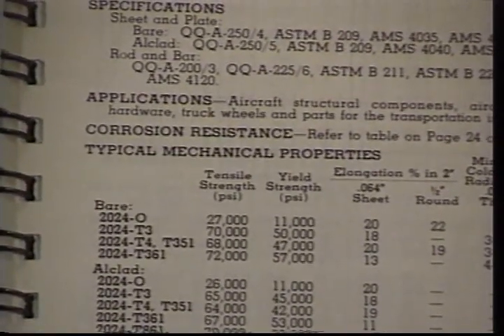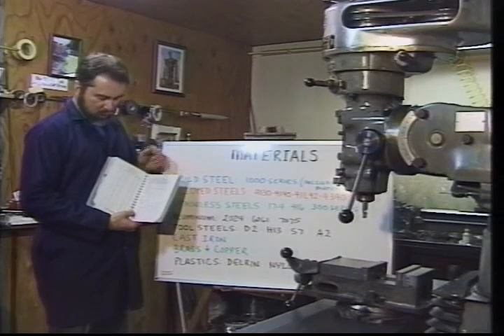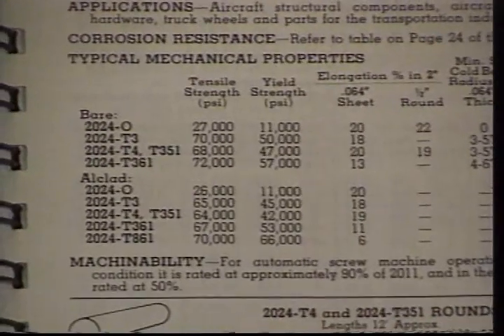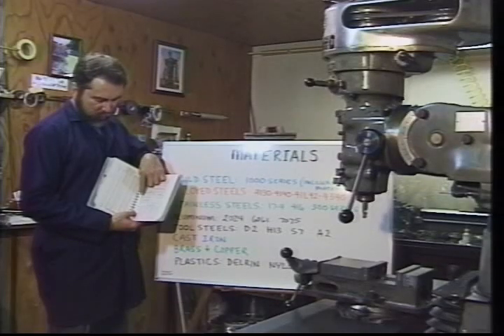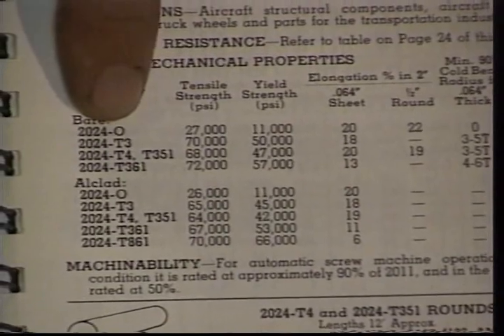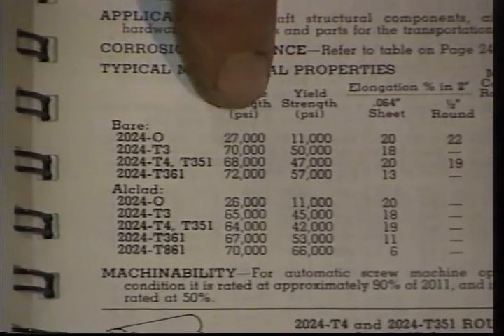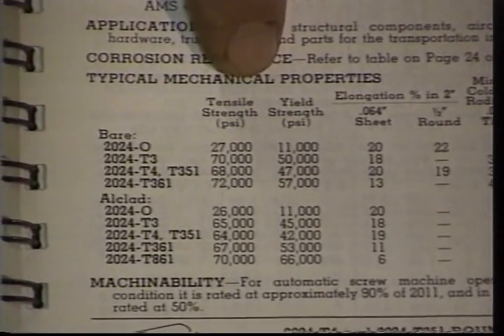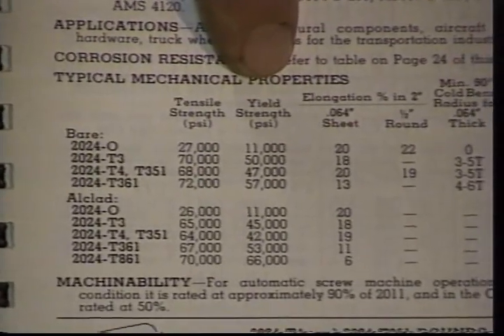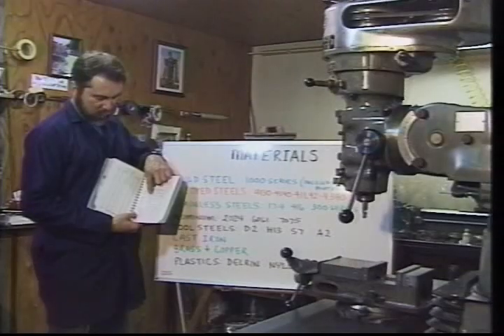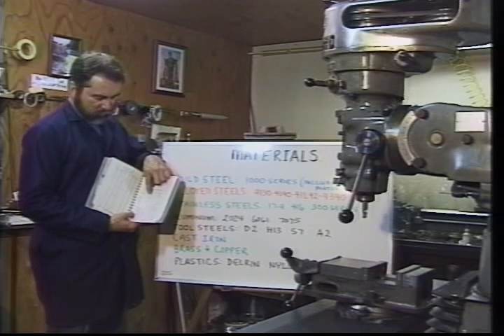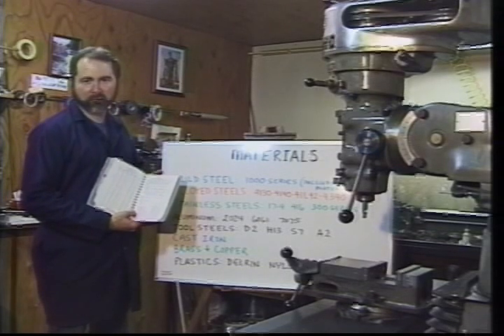We have specific applications, primarily used in the aircraft industry for structural components, tooling, truck wheels, etc. It also will tell us the machinability of this specific alloy in its different heat treatments. It'll also show the heat treatment of the material. Remember the T designations after the 4 numbers of the alloy, T3, T4, T361, etc. Look at the tremendous difference from the standard mill run or annealed condition with a tensile strength of 27,000 psi and a yield strength of 11. Now in a heat-treated condition of, let's say, T361, that same tensile strength goes to 72,000 psi and the yield to 57,000. So approximately 3 to 5 times the strength when we heat treat that alloy.